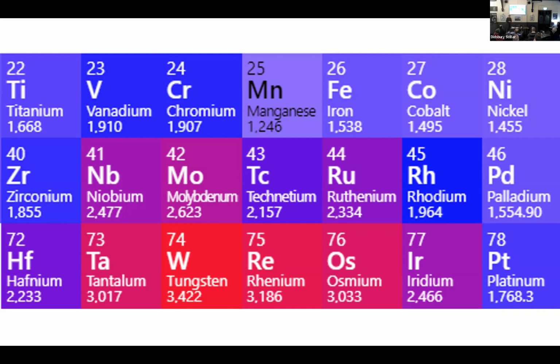So we don't just have helium getting generated in it, we have literal lead into gold going on. And over time, the tungsten will actually transmute into rhenium and osmium. And this is literal lead into gold because osmium is not too far off the cost of gold. And so it's not even that the atoms are in different places. We've got different atoms in there.